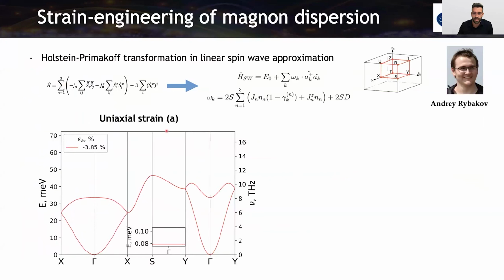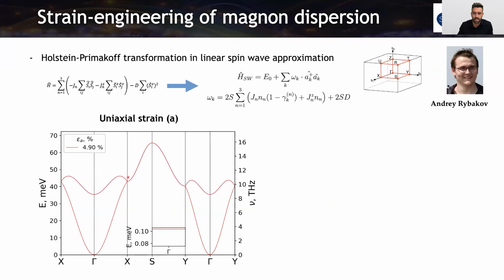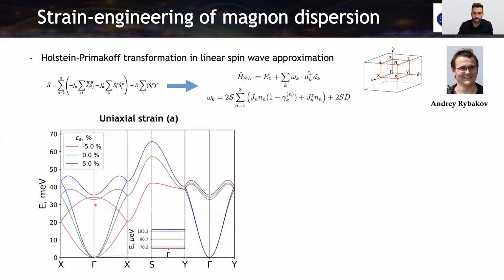This also affects, of course, the magnon dispersion. Here we are calculating via the Holstein-Primakoff transformation how the magnon dispersion evolves with an expansion of the material. So with this expansion of the A-axis, in this case by uniaxial strain, we are having this increase in the dispersion. This is the final plot here, and especially we are affecting the magnons in the gamma X direction. So it's a selective control of magnons in the material. With this 5% increase, we can observe this blue line.